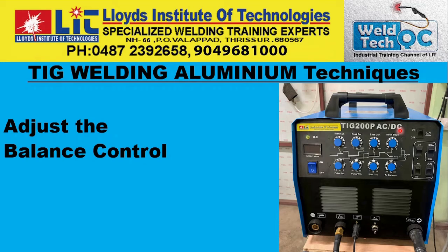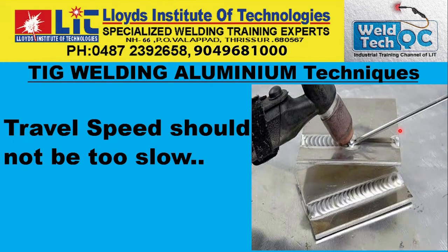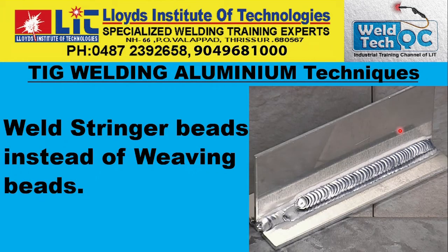You can start with 50-50, 30-70, or according to the requirement of the base metal. And travel speed should not be too slow while you are welding aluminium. That please be noted. And it's always recommended to use stringer beads instead of weaving beads.